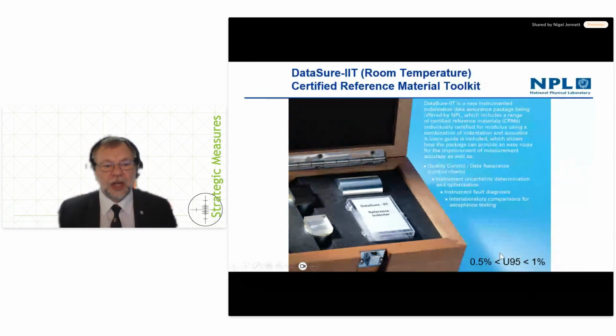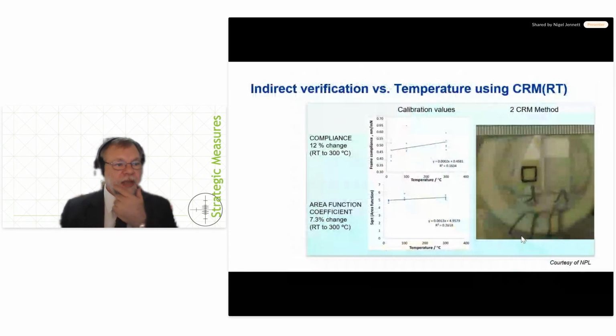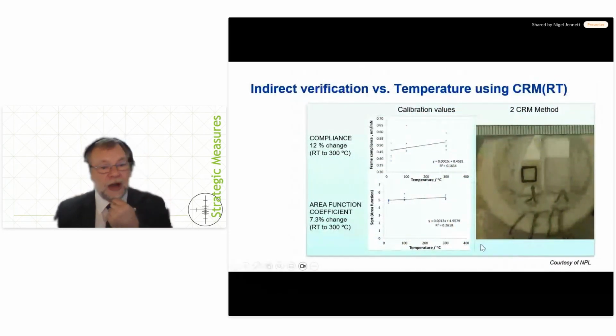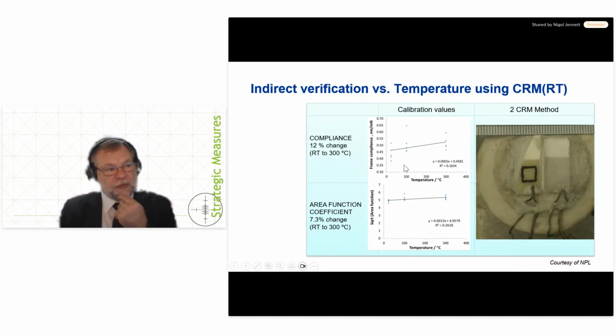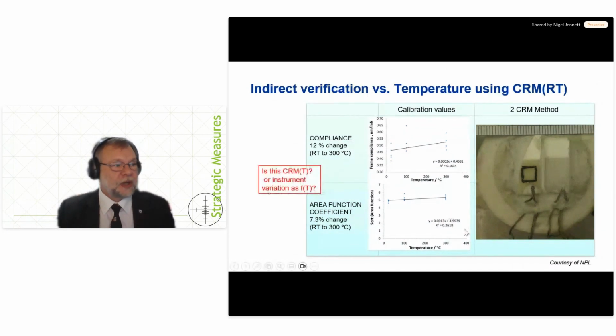And so you can look at your machine and check its working and look at its repeatability at room temperature. If you chop bits of it up and stick it on a hot stage, what you find is that you get a 12% change in frame compliance and a 7% change or so in the area function of your indenter tip as a function of the first 300 degrees of temperature that you increase. So, question, is this a measurement of the change in properties of the reference material as a function of temperature, or is this a change in the frame compliance of your stage as a function of temperature, or the thermal expansion or other change in your indenter as a function of temperature? You don't know until you calibrate your certified reference material.